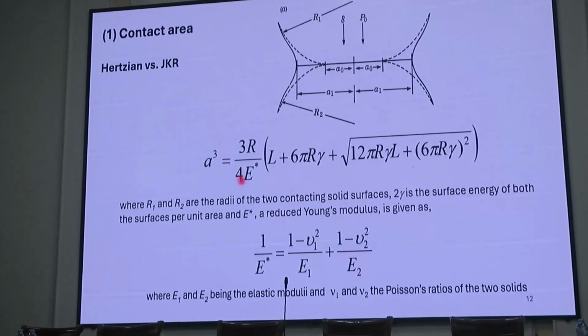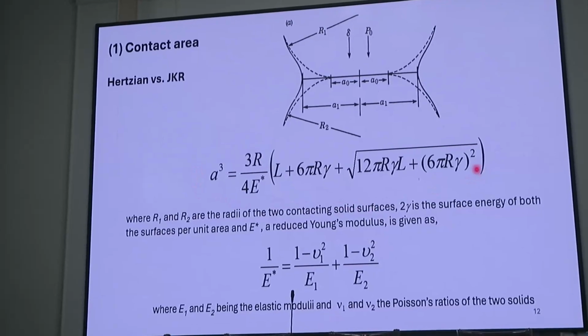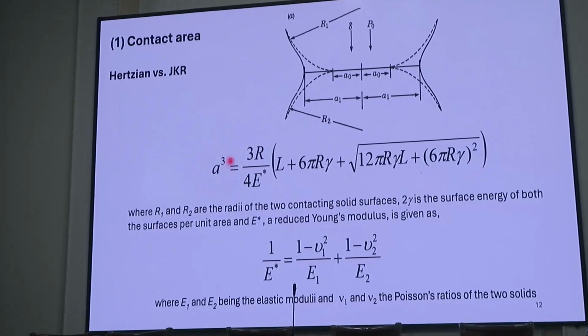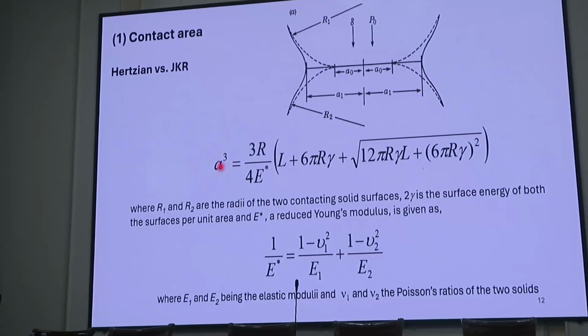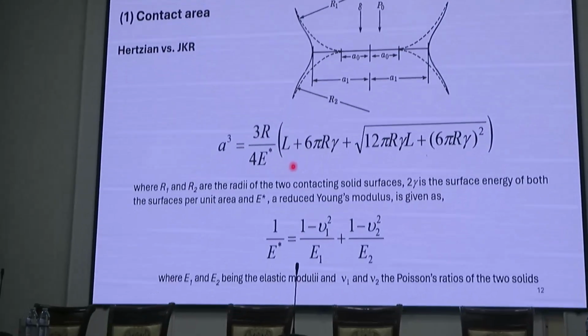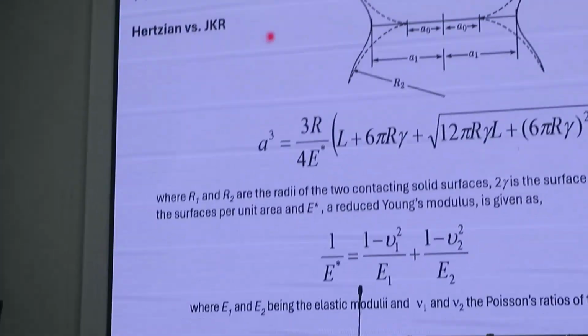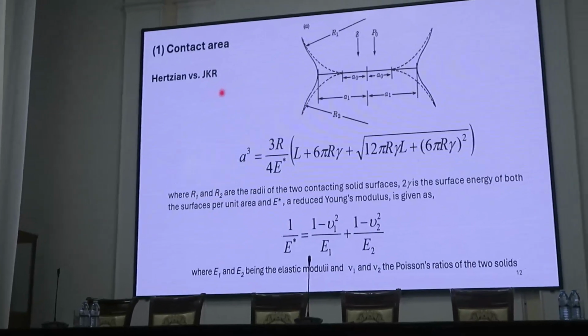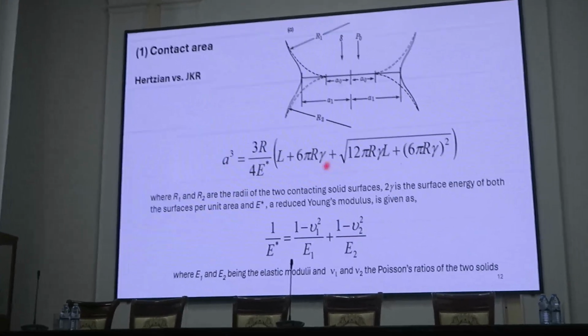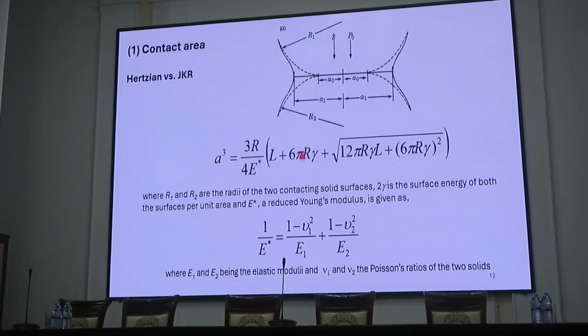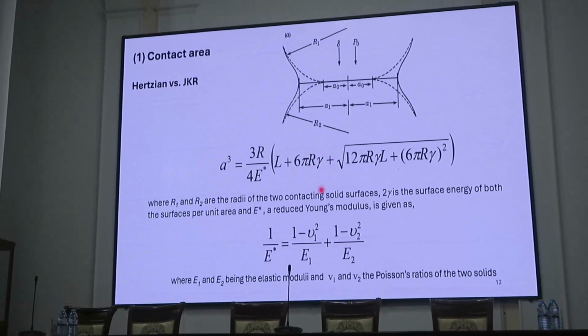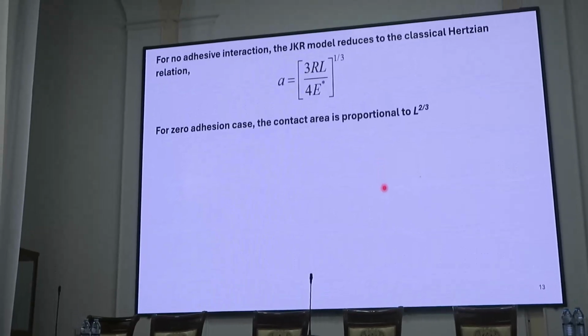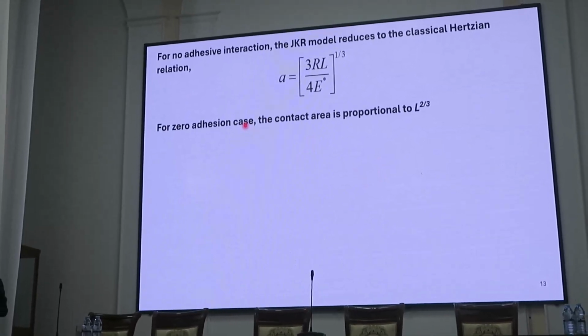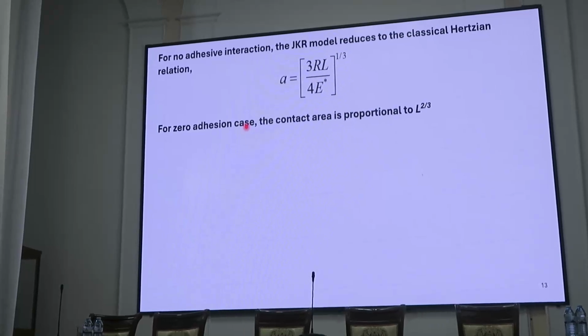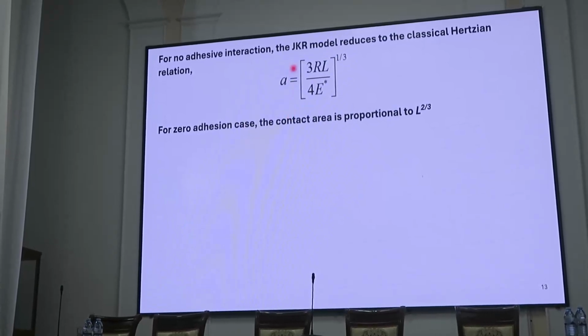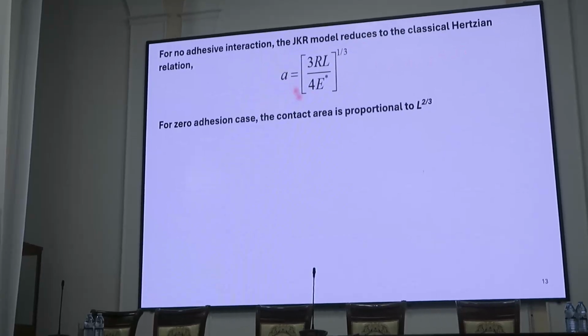For example, contact area: we know that the Hertz contact equation can be used for finding out the contact area, and especially for softer contact, we should use the JKR model rather than the Hertz contact model. So this is the JKR equation. Here, the only difference is that surface energy has become an important part of this. If you consider that there is no effect of surface energy, that means there is no adhesion effect, then the JKR model basically becomes the same as the Hertz model, which is given here.